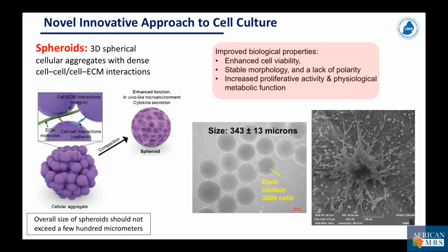Now, these spheroid systems have shown improved biological properties in terms of having a more stable morphology, lack of polarity, increased proliferative activity, and physiological metabolic function. This figure here shows an optical photo of spheroids where the average size of the spheroids is approximately 343 microns, and each of those spheroids contains approximately 2,000 cells. And here you have a scanning electron microscope image where you can see the spheroid cells migrating onto the nanofibrous mat.